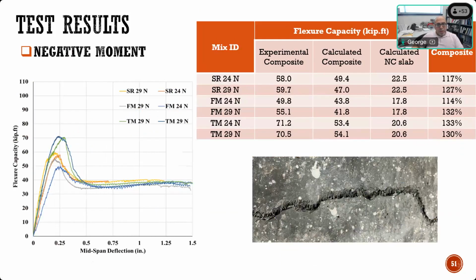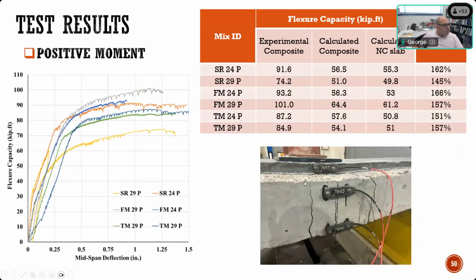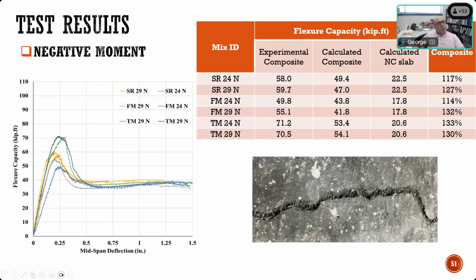Here's the one. And just to show the failure here, when you have a positive moment, you just fail the conventional concrete by cracking it and yielding the bars. And in the negative moment, because UHPC is in the tension, you get the crack localization, and you see the fibers bridging the gap until they completely pull out of the concrete. So we expected that behavior, and we saw that in the testing. So we're very comfortable that it behaved as predicted.